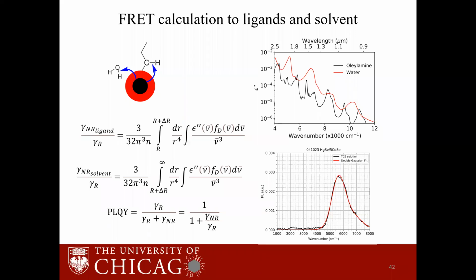And we have the ligand shell starting from the quantum dot surface to around 1 nanometer. So for the ligand FRET, we do this radial integral from the surface to the ligand end. And for FRET to water, we do the integral from the end of the ligand shell up to infinity. And so that will give us the non-radiative rate, and the quantum yield is calculated. Yeah, so the quantum yield is found by a ratio of the radiative to non-radiative rate by that formula.